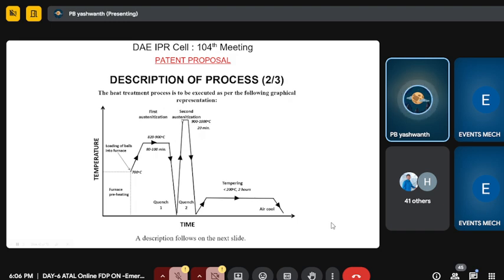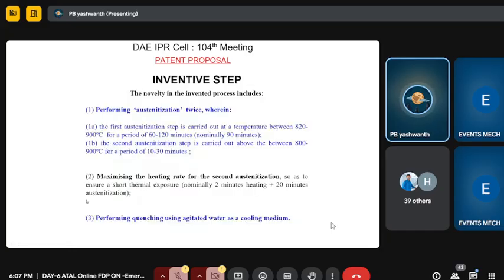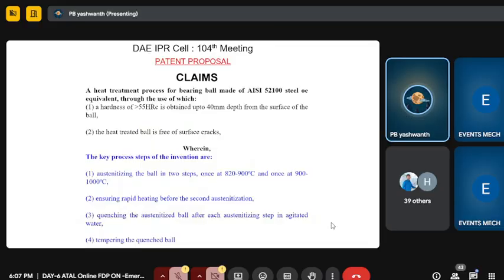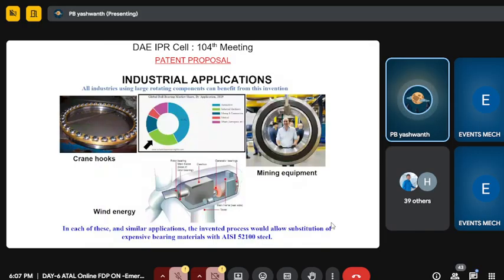In the second austenitization, previously we had a soaking time of 100 minutes, this time we have 20 minutes soaking time, and suddenly we quench it, and finally the tempering process takes place for 2 hours. So we carried out around 13 to 15 trials to achieve this particular hardness, and these inventive steps made us have a patent in that.